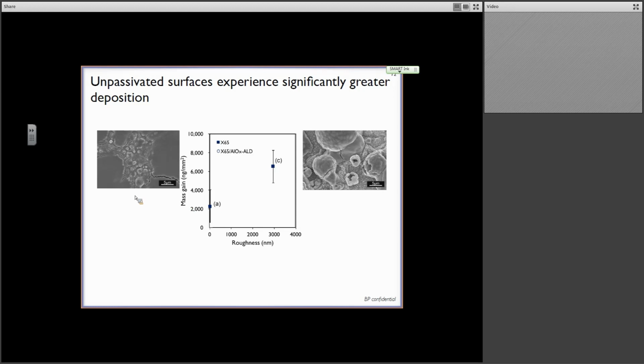This micrograph is a relatively smooth X65 steel. So it's a high strength, low alloy steel, often used in pipelines. And you can see this is no longer a smooth surface. After the fouling process, we have large depositions on the surface here, and you can see that measured as a measure of the mass gain. Right? And these are kind of smooth over here, and then these big mud cracks, and in between these islands, we have these globular structures.